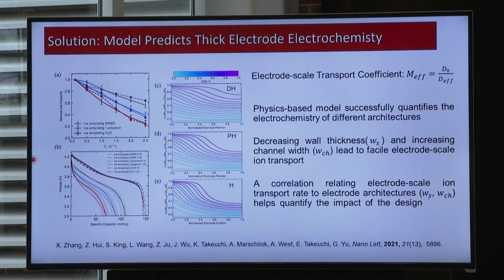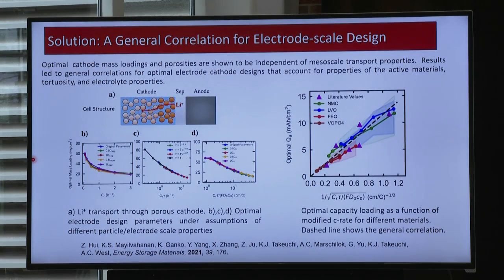And we, working in conjunction with some of our modeling colleagues, developed some models where we could really predict, as a function of the discharge rate, what the voltage profiles would look like for these various electrode designs. And interestingly, when we first started this, we thought that the models would be fairly specific to a given chemical system. But as we started looking more broadly, it turned out that the models were pretty broadly applicable, that in a general sense, independent of the chemical system, as long as it's an insertion cathode, these models hold up, and we can relate the rate capability and the electrode design for almost any chemical system that's relevant. So these are continuum models, I should explain.